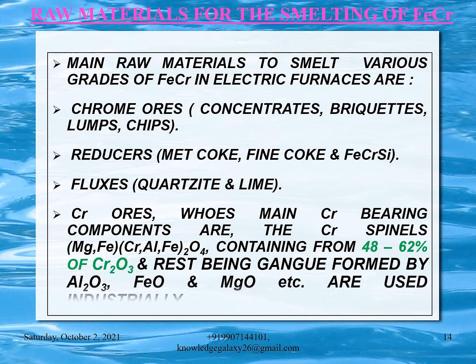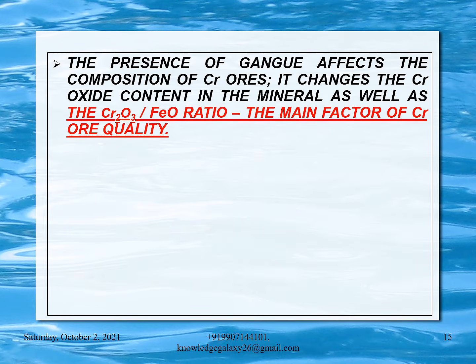Chrome ores, whose main chromium bearing components are the chromium spinels (Mg,Fe)(Cr,Al,Fe)2O4 containing from 48 to 62% of Cr2O3 and the rest being gangue formed by Al2O3, FeO and MgO etc., are used industrially. The presence of gangue affects the composition of chrome ores. It changes the chromium oxide content in the mineral as well as the Cr2O3 by FeO ratio, which is the main factor of chrome ore quality. I repeat, Cr2O3 by FeO ratio is the main factor of chrome ore quality. Do remember this?